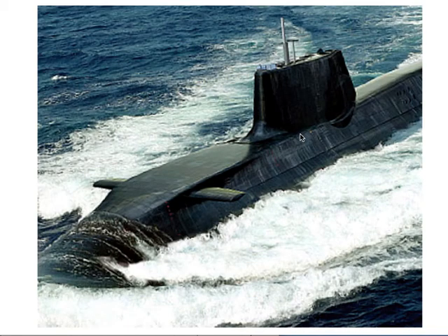And then the project was actually initiated by the Navy, because they needed to weld submarines. And because the steel is a high strength steel, you can't heat treat it afterwards. You can locally heat treat a weld by putting an electrical blanket around it, but that would compromise the properties, right? So once you deposit the weld, you don't want any further heat treatment. And the second issue is distortion. When the components are able to move, then the residual stress is relaxed, but you get distortion as a consequence, right? And you can't tolerate that on a big object.